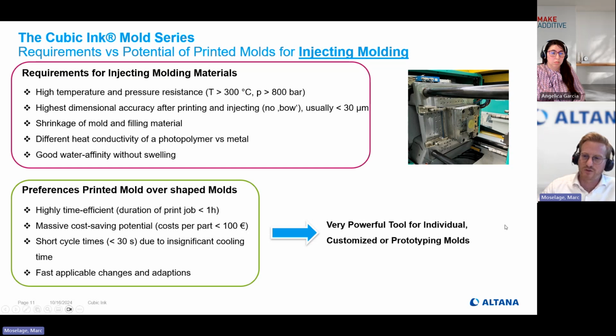It's something you see on the picture here. This is an injection molding machine, and you see the mold. This is this yellow cylinder. It is just placed there. It is not screwed, not fixed. It is placed into a holder, which can be easily prepared from aluminum. Then the injection happens, and the entire mold with the filled material gets injected. So the cycle time is usually a couple of seconds.